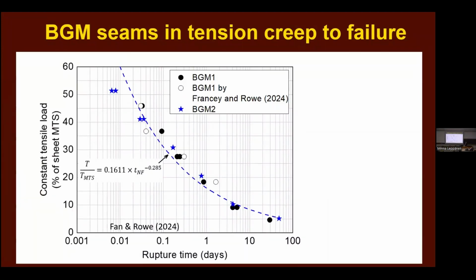Now, let's take tests like that and document them. So here we're plotting the constant tensile load that was applied versus the time to rupture. Data is shown for two different people doing the work and two different geomembranes. And you can see there's a pretty clear relationship. As the stress goes up, the time to failure goes down. Now I'm going to pick 30% of the strength. Why do I do that? Because when we do a stress crack on HDPE, we do it at 30% of the yield strength. So when we talk about what's the stress crack resistance, it's at 30% of the yield strength for HDPE. So let's talk about what is the failure time at 30% of the strength of this particular material, and it's about 0.1 of a day. Not a lot of time.